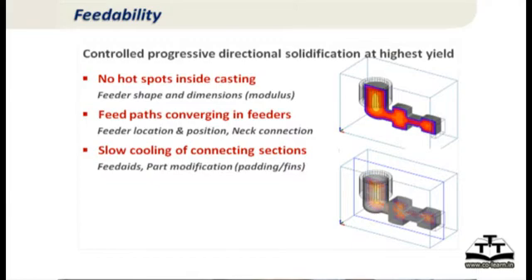I control the feed path by the right position or location of the feeder and the right size of the feeder neck. Third, we want to have proper cooling — not too fast cooling, which is bad. I want a controlled cooling rate. How do we control the cooling rates in different parts of the casting? By combination of feed aids. We look at entire feed aids in a separate lesson, and only feeder size and shape in this part.